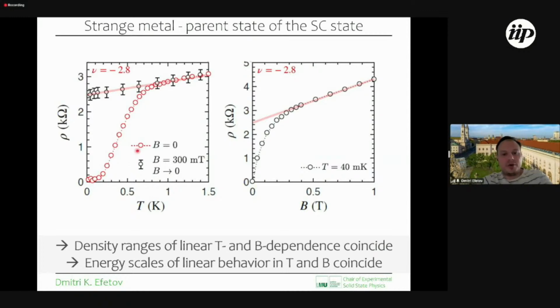And we would be able to apply a perpendicular magnetic field to kill the superconductor and to really look at the metal which is left when the superconductor is gone. And really, we did this, and we find that even when the superconductor is gone at 300 millitesla, the linear temperature dependence persists.